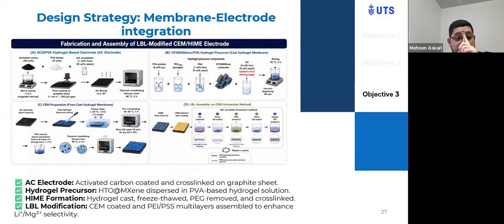For this target, the design strategy was producing a novel membrane electrode. First, the activated carbon electrode was prepared and cross-linked, based on glutaraldehyde, where PVA was used as a binder. Then the HTO MXene developed in the previous chapter was put in the PVA matrix to provide the membrane on top of that electrode, and based on the hydrogel casting, freeze thawing, PEG removal, and cross-linking, an interconnected porous structure was formed.